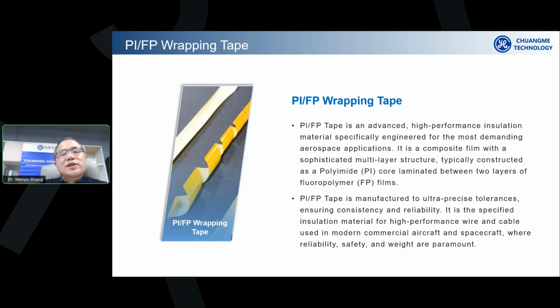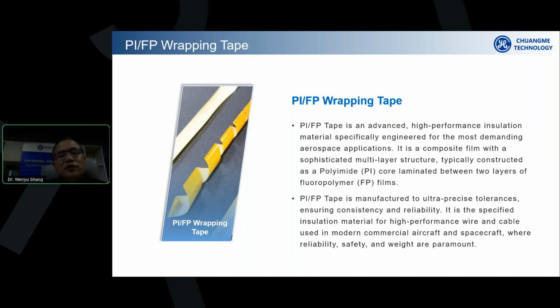In the overlapping parts of the wrapping cycles, the upside fluorine polymer layer is in contact with the bottom fluorine polymer coating of the other side of the PI tape. When we pass the cable through an oven, these two fluorine polymers melt and form a continuous, non-cracking insulation layer over the wire.